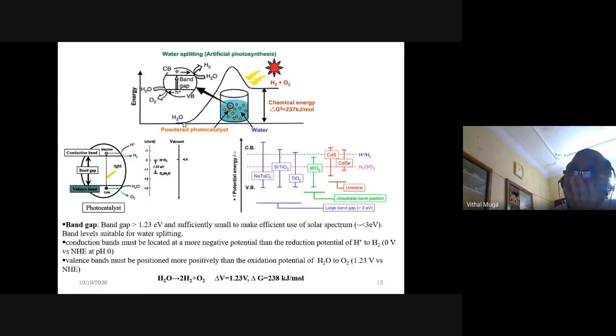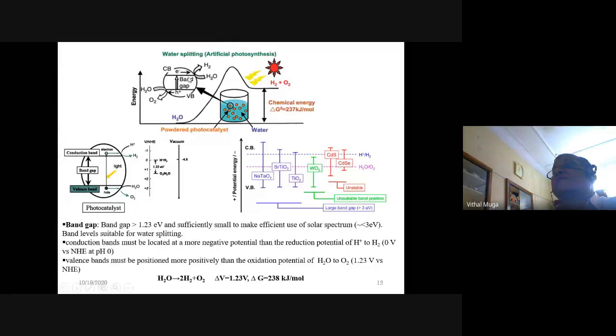This also we have done in our laboratory, but unfortunately the amount of hydrogen that is being generated is not sufficient. It is actually in microliters only, because so far the benchmark material is strontium titanate, SrTiO3. I have shown SrTiO3 here, which shows something like 200 to 300 microliters per hour per gram of the catalyst. This is the highest efficiency so far achieved, but we are in microliters only, whereas we want liters and liters, tons of liters of hydrogen gas. Once again, the process is very simple: we have a semiconductor, you irradiate it with sunlight, then electrons and holes are created, and the electrons will react with water to form hydrogen and oxygen.